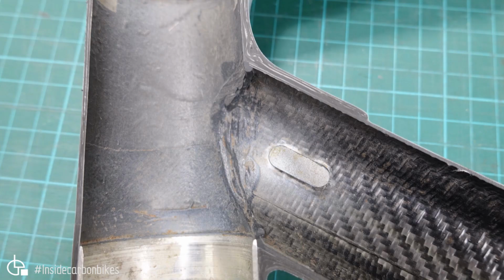So the only other thing to add was we have seen cases where these cable guide inserts, particularly on the top tube, on the non-drive side, you get crack indications right on the edge of the forward and aft faces. And often we've seen cases where there's been insufficient adhesive in those inserts when they're bonded in, and hence you get a crack occurring because they're not really bonded in properly. So that's the only other thing that we've seen on these frames over the years.